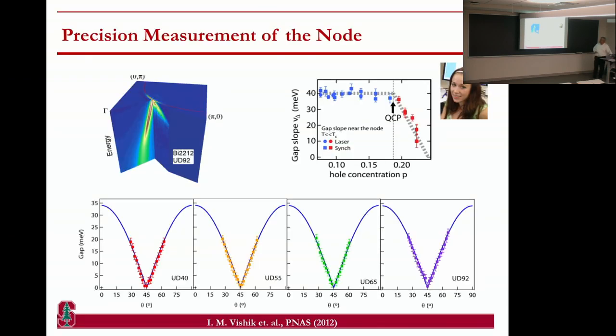And of course, we saw in the talk by ZX Shen a couple of weeks ago, also something dramatic happening around the same doping, in a different set of materials. He was measuring the superconducting state down at zero temperature. And when you looked at this velocity near the nodal point of the superconducting state, it was essentially doping independent all the way up to some doping, which is not something you get out of BCS theory, because the Tc is varying a lot. Roughly speaking, as Tc goes up, the gap goes up. As the gap goes up, this slope should go up too, but it doesn't. On the other hand, on this side, it follows exactly like you expect: the Tc is going down, the gap's going down, the slope's going down. All right, I think that's the summary of it.